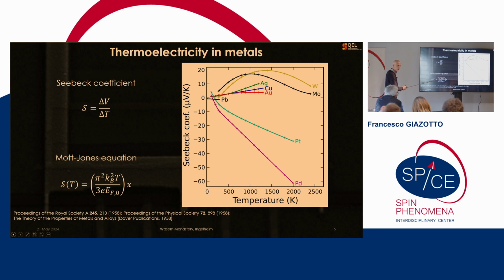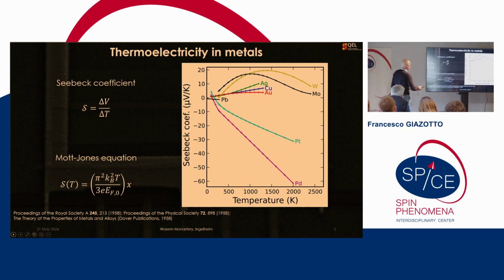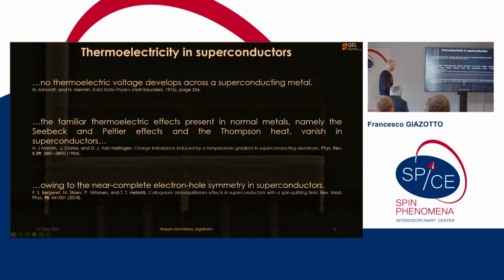By decreasing the temperature, you completely suppress the Seebeck coefficient in the system. So going down in temperature, for instance in quantum systems or in quantum technology, we would not expect this to increase; you go down to very small values. This is just to say that metals in general are very poor thermoelectric materials.